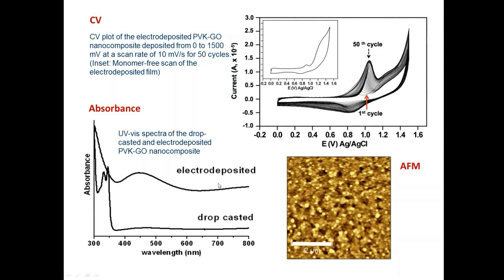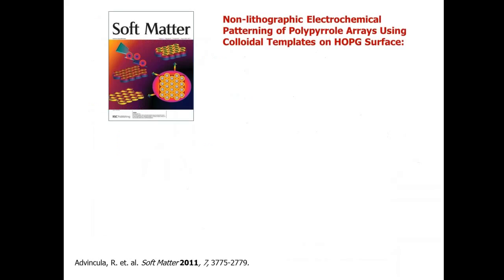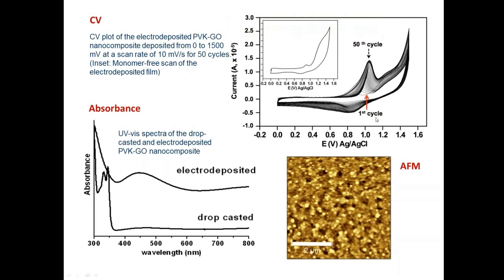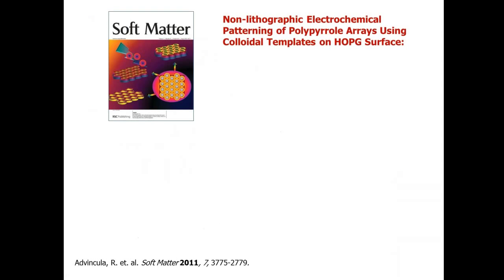This method, in fact, we patented as a way of pinning down the graphene oxide by using a precursor polymer that can form a barrier material, an electroactive barrier material as well, deposited on a conducting substrate. We actually have several uses of this, and I'm not allowed to show them because of some patent disclosures, but essentially this is a way of modifying conducting surfaces or making a coating which can have some anti-corrosion properties.